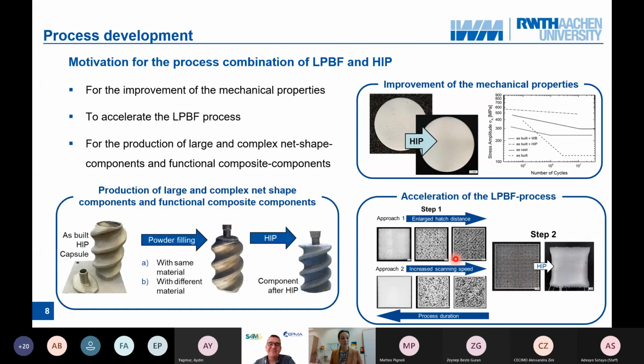And that leads to the third approach, and that is that you only build the dense shell with additive manufacturing and fill in the powder afterwards. Then you close the capsule, evacuate it, and put it in the hot isostatic press, and then you get the final component. And when you accompany that with finite element simulations, you can design the shape of the capsule so that you get your desired geometry after HIP. There are some simulation programs that are able to predict the shrinkage during HIP, and with those simulations, you can design the capsule before HIP to achieve the desired geometry.